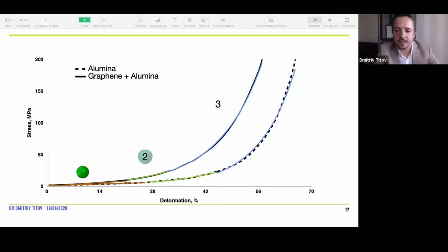The second stage corresponds to deformation from 20 to 45%. It is characterized by a very steep nonlinear rise in stress with increasing deformation. The particle movement is due to the accommodation or adaptation of them among themselves, and on the other hand, due to the deformation of their volume. In the third stage, when the stress is increased over a wide range, only small changes in the deformation occur. The compaction process is carried out mainly due to the growth of the contact surface during the particle deformation. Let's look at the first stage.